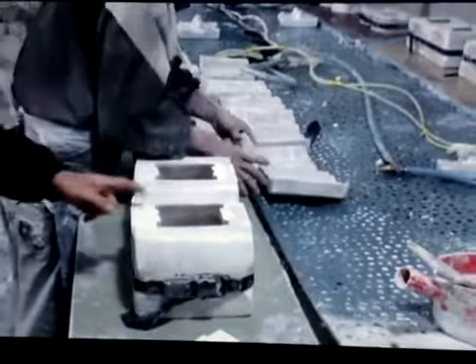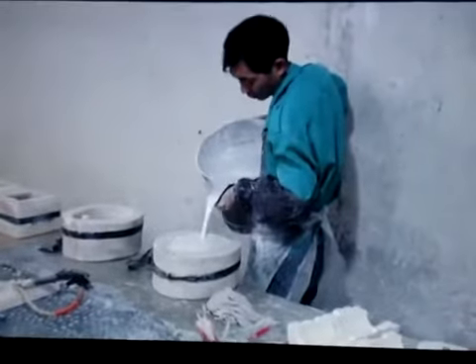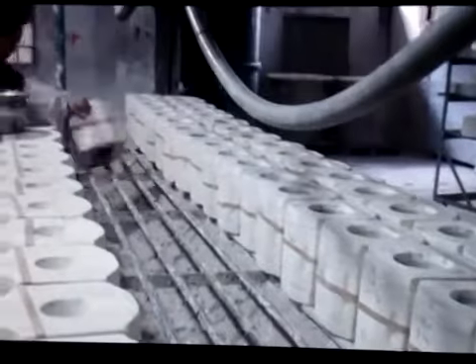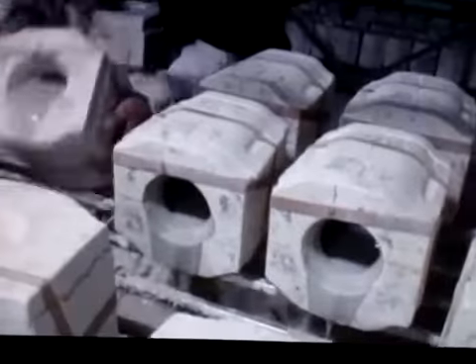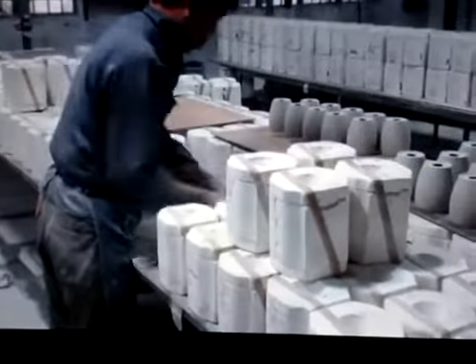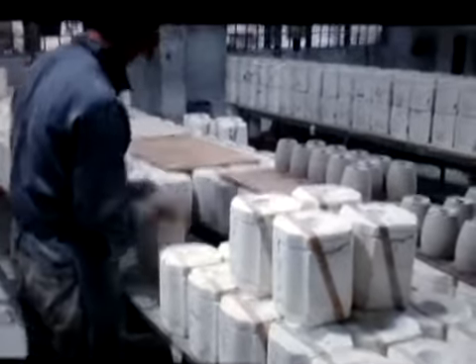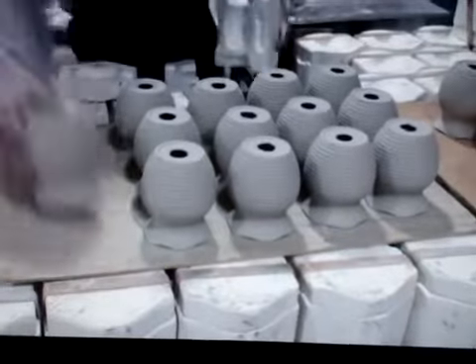The right type of clay is carefully selected for qualities such as color and texture that complement the design. It's reconstituted into a slurry and poured into the production mold. The clay sets for a specific, carefully monitored amount of time, hardening from the outside in as the mold draws moisture from the slurry. When that time is reached, the excess slurry is poured out and will be recycled. The pieces of the mold are carefully removed. The object within is called greenware, and it's beginning to take on the look of the final ware.